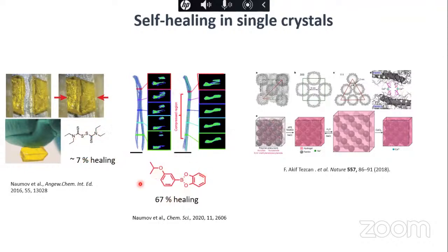And the other example is, here you cut the crystal into pieces, and then you again compress them under some plates, and put some pressure for 24 hours. In this case, it regains about 67% healing. But in none of these cases was the crystallinity studied at the healed junction. As you can see, the crack is visible.